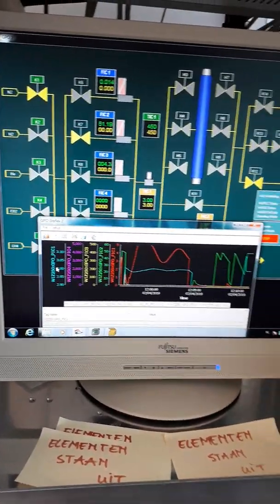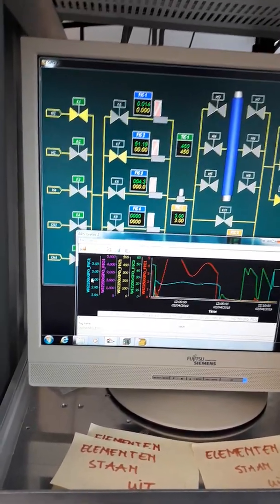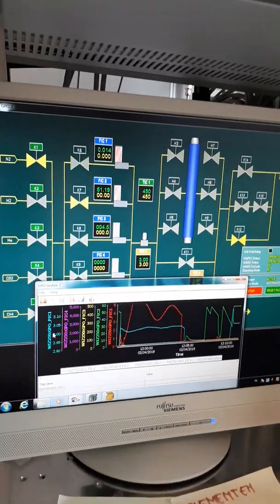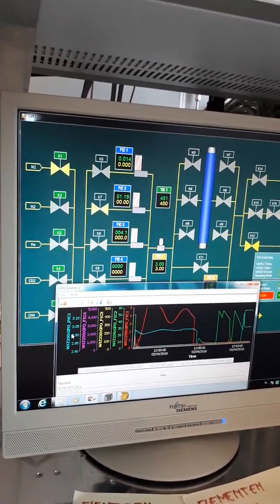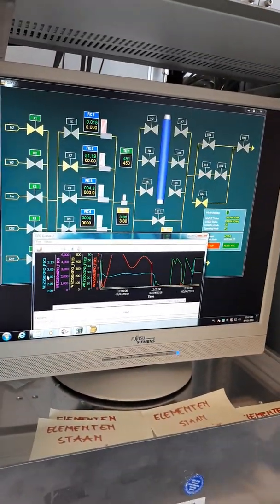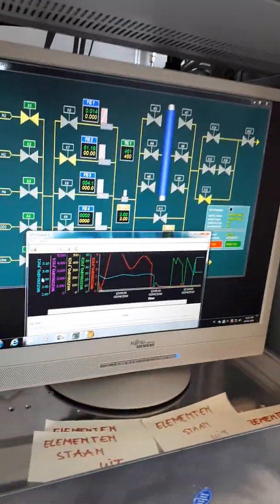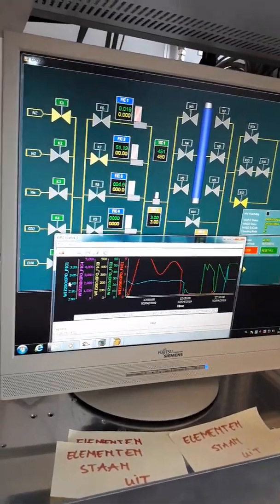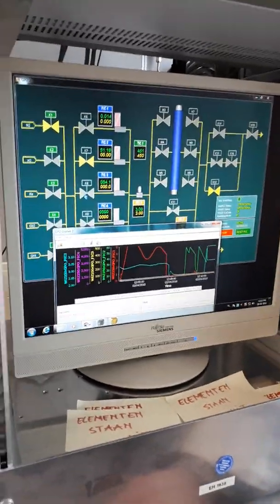And then the question is whether there is already something in the support in that original part, or is it something external that we couldn't see? So this is the inner porous support. We've coated the alumina layer. The first thing to be checked on this layer is the calcination temperature of the alumina. Maybe also something in the suspension or preparation, or the pre-treatment. There can be all kinds of things, but the calcination temperature is at least something relatively easy to check, in case there's a wrong setting. For the intermediate phase, the calcination temperature has to be high enough to give rigidity to the layer that we apply.